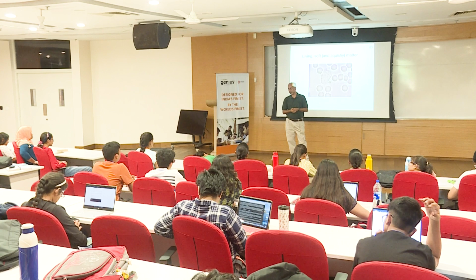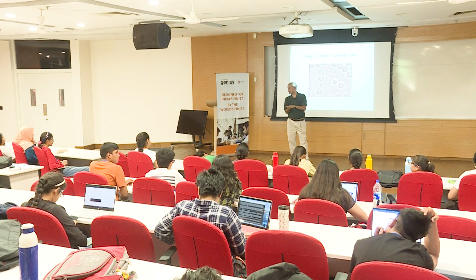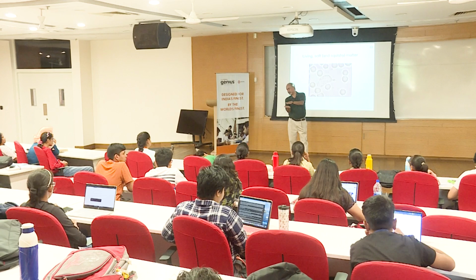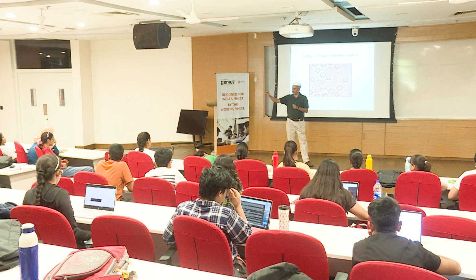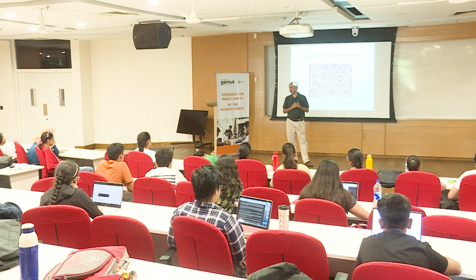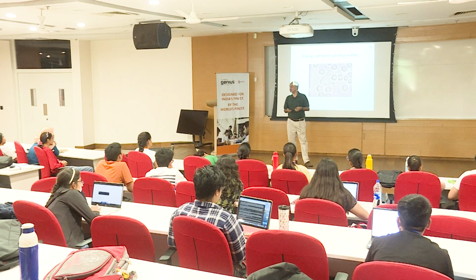So now I can do this slowly, then faster, faster, faster, and I'm going to measure the resistance. If the relationship between the resistance and the speed at which I move it is linear, a straight line, so the faster I move it, the larger the resistance is, that's called a Newtonian fluid. On the other hand, suppose I do it faster and faster and it suddenly becomes easier, there's less resistance. That's a non-Newtonian fluid. In fact, the technical word is shear thinning fluid.